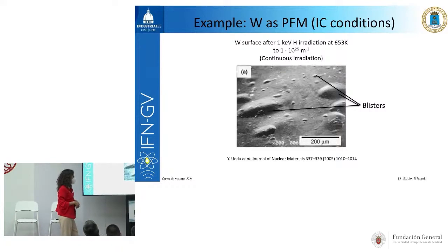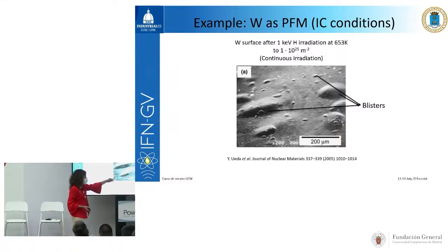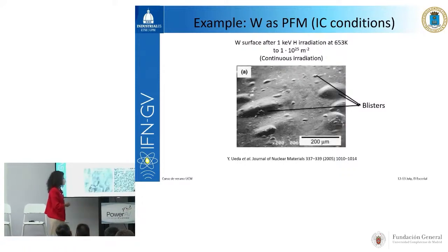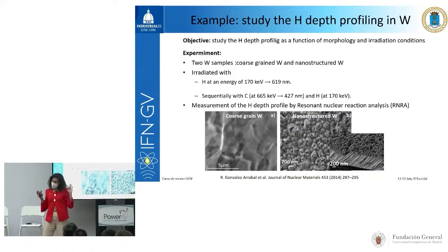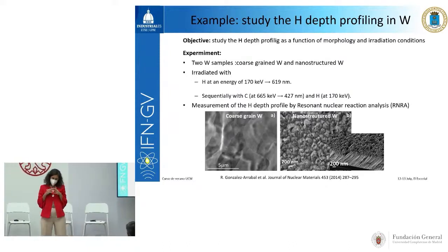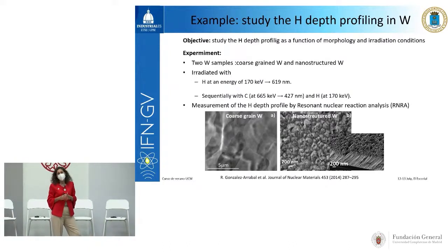Okay, so this is another thing I wanted to tell you. We have a very similar behavior when we were irradiating the samples not with helium but with hydrogen at high energy. Again, we see that we have some blisters. And in this particular case, this is particularly interesting because we were studying the behavior of nanomaterials under irradiation. So we know that the coarse-grained tungsten is not going to work under inertial fusion conditions, and we were trying to test the capabilities of nanostructure in tungsten. What is going to happen if we introduce a large density of grain boundaries into the material?